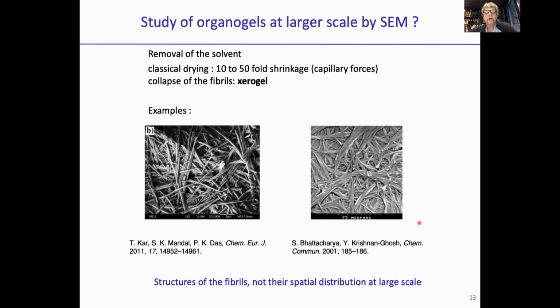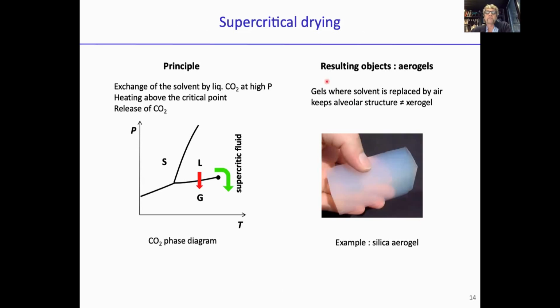All right. And that's why we developed what happens if we dry in a different way, by supercritical drying. It consists of exchanging the solvent by liquid CO2 at high pressure, like in this diagram. This is the classical drying, when we start from a liquid phase and just evaporate it. And the supercritical drying consists in exchanging the solvent. So we are somewhere at high pressure around here. We heat the CO2 above the critical point, and then we release the pressure. We let the CO2 escape. So what we get is something that has no more solvent, but which has not gone through this threshold between liquid and gas. So it's a supercritical drying.